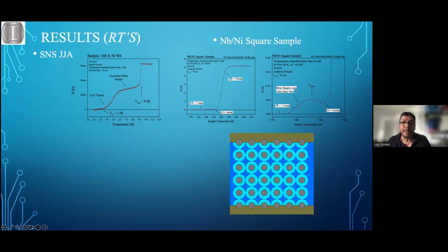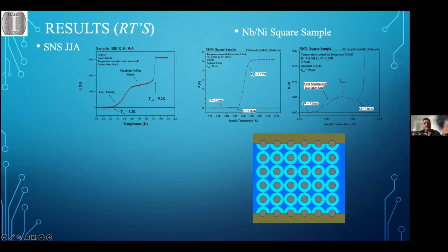But right in between and where the nickel is, it's not fully superconducting. In fact, there is a weaker superconductor. It's actually not superconducting, because we're measuring a resistance. But maybe somewhere in between, the farthest away you can see from each one of these dots, there might be a pocket right there of full superconductivity.